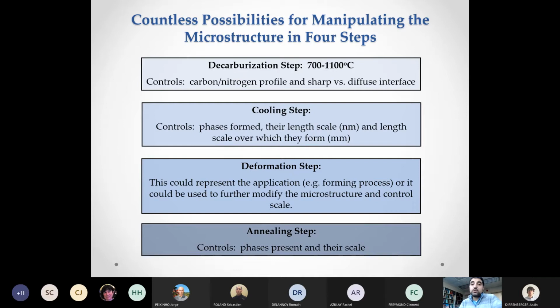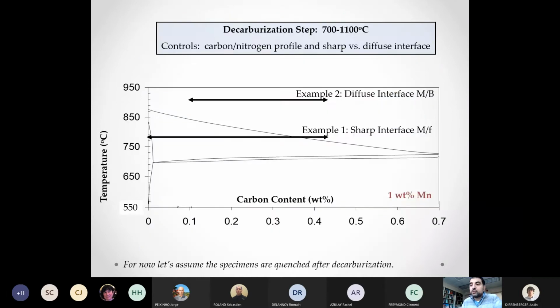And after that, there is the cooling step, and that determines which phases we get, if we get bainite, martensite, pearlite. And afterwards, we could use the material immediately, or we can deform the material and subject it to subsequent annealing in order to modify the microstructure again. So I'll give a few snapshots of what happens in each one of those steps. So the first step is the decarburizing treatment.